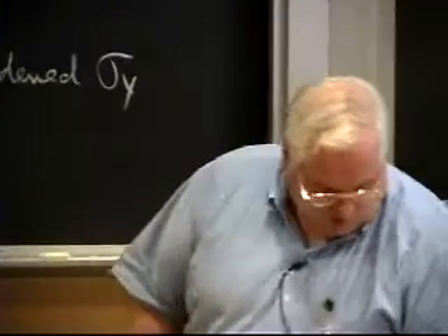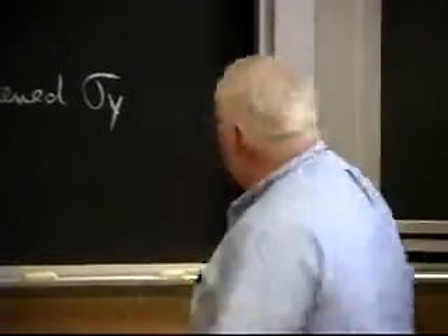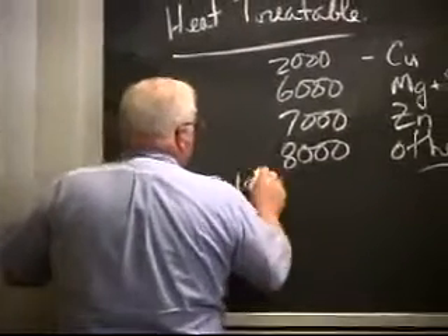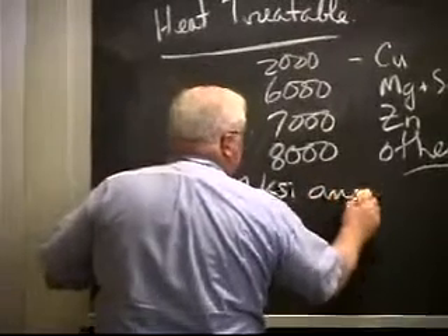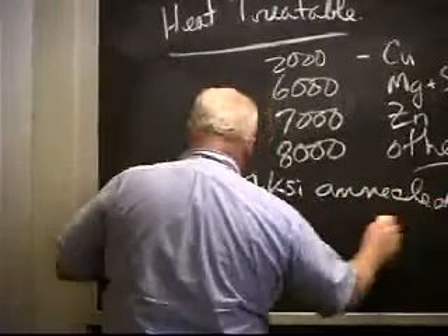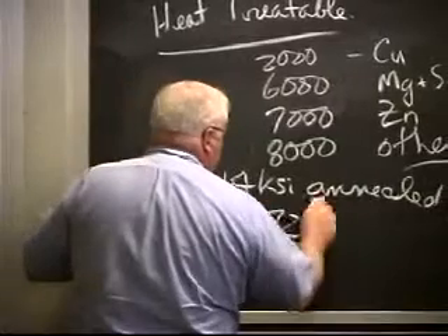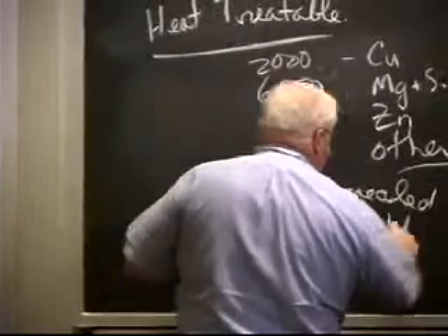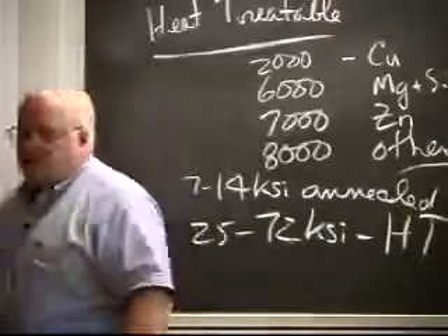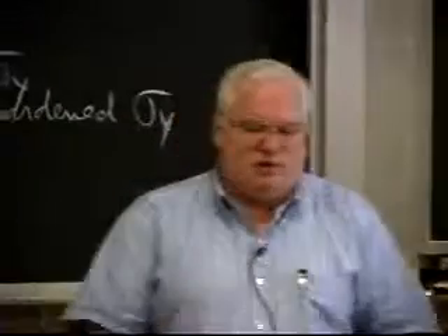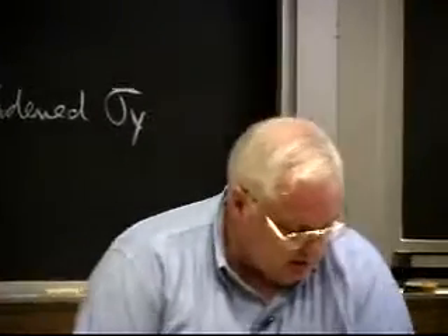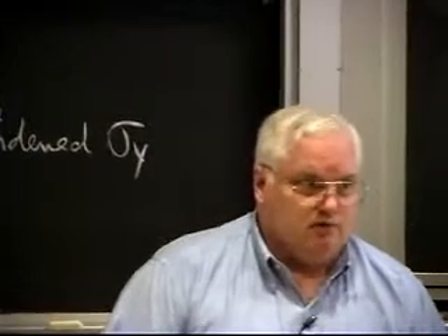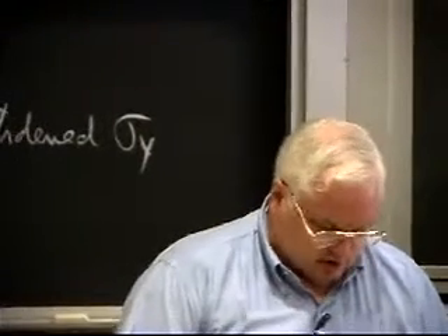In any case, to finish up for today, the types of strengths I can get with these alloys are 7 to 14 KSI annealed, and I can get 25 to 72 KSI typically heat treated. So 72 KSI, that's yield. That's significantly stronger. That's double the strength of a garden variety steel. It's nowhere near the strength of a heat treated steel. I mean, it's less than a third the strength of a heat treated steel,